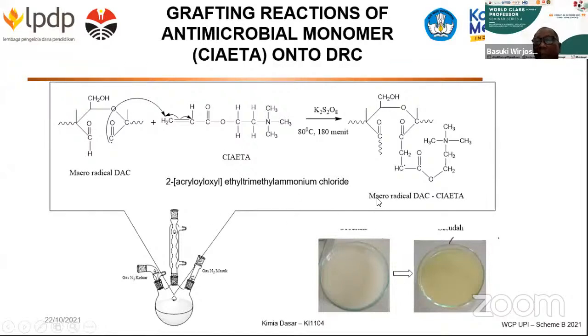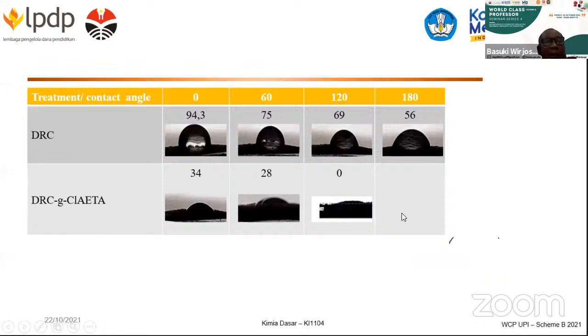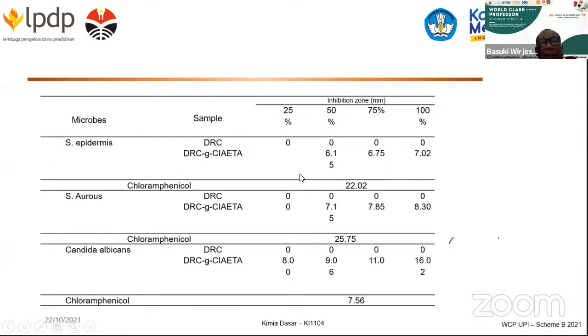Okay, and then we can produce some cellulose product which is grafted with the salt, this antimicrobial compound, and we tested the antimicrobial activity of this compound. And then we tested also the contact angles. This is the pure cellulose. See, the contact angle is very high, which means that this is very hydrophobic. After we graft it with the antimicrobial compound, the contact angle goes down, even to zero. This means that it is very compatible. And this is the antimicrobial result of the compound we produce here.